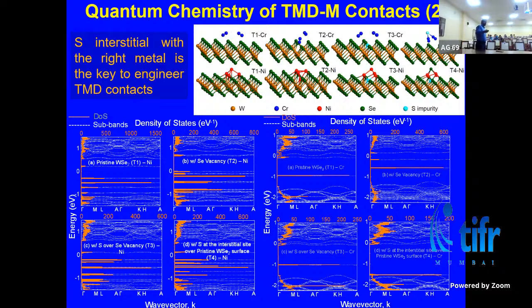With the conduction band closer to the Fermi level, you basically have a lot of donor states. And if you have a lot of acceptor states, which brings the Fermi level closer to the valence band, it makes the system p-type, right? So you found that depending on what defect system you choose, vacancy or interstitial, and the metal that you choose, you can selectively introduce these donor states or acceptor states. So now we knew that we have to deal with certain metal systems and certain interstitials to introduce these donor states or acceptor states.